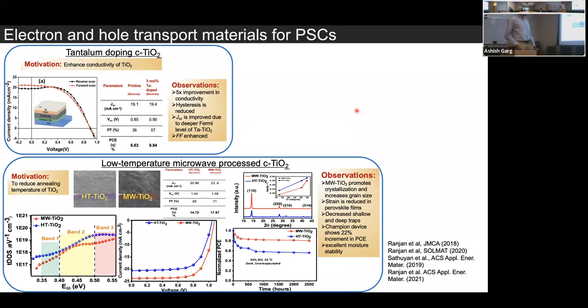Generally, the TiO2 that you process in the lab as an electron transport layer requires about 500 degrees centigrade processing, which is fairly high. Most glasses soften at this temperature, so it's not a desirable thing. Instead of high temperature thermal processing of TiO2 on a hot plate or in a furnace, we did microwave annealing of TiO2, only for a minute or two, and this does wonders. The temperature measurements are not very accurate in microwave, but whatever optical methods we have tried, the temperature seems to be lower. The important thing is the device efficiency improvement: it improved by about 3% or 4% in the microwave processed sample.